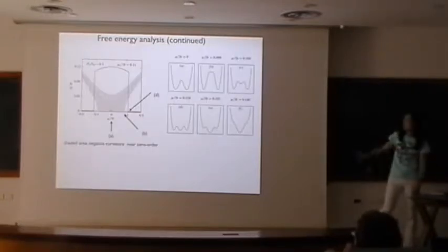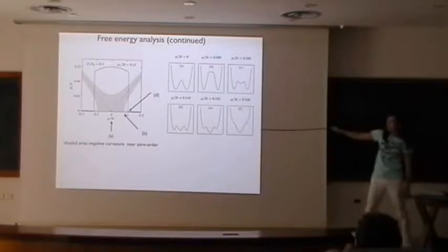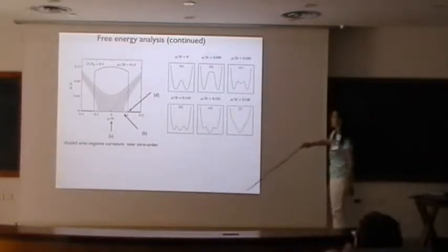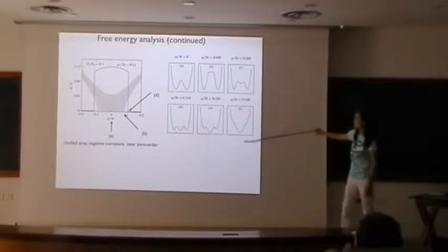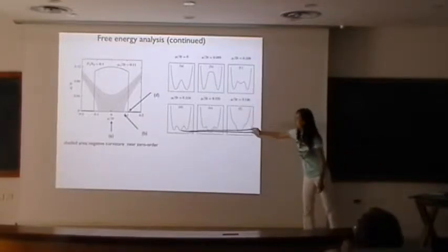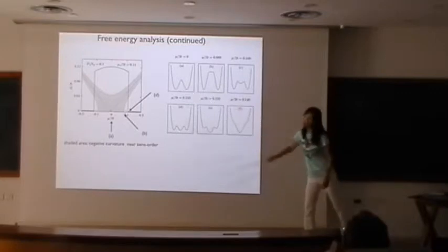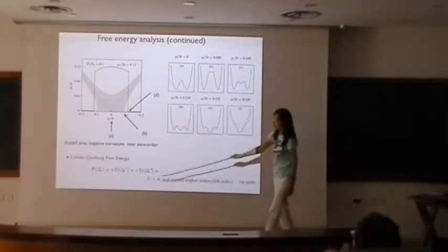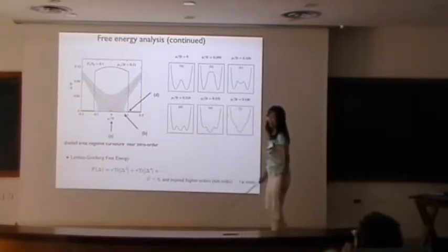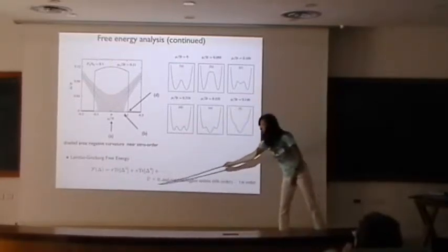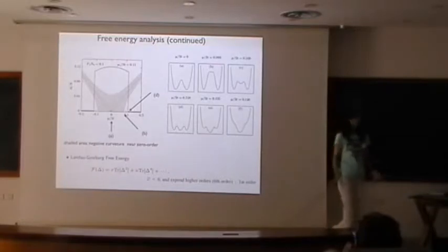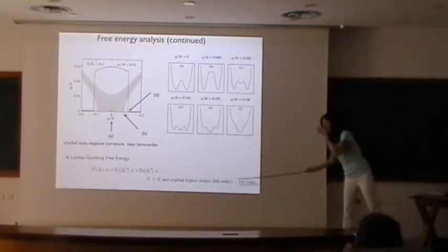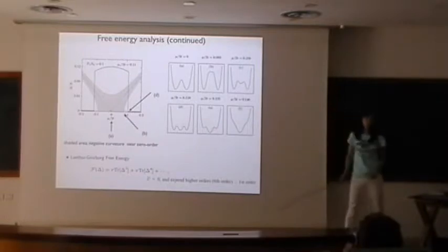I just want to show why that has the first-order transition. You can go from here to there and back here. In the isotropic phase, this delta is zero. As you go along here, you can see the T minimum occurs and it becomes like a cube. So that tells us that in the Ginzburg-Landau free energy analysis, the quartic term is not positive, it has to be negative. And that means the free energy is not bounded, you have to go to these higher orders. And so you have to expect to see a sixth order term, and that leads to the first-order transition.